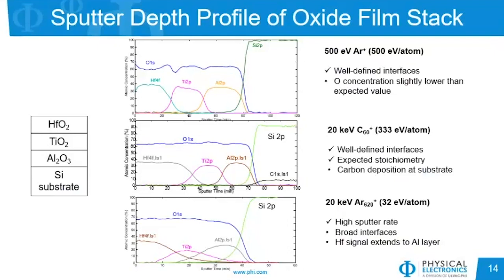So I'll point out that the stoichiometry for both the C60 and the monoatomic argon tend to be closest to the actual values. In the argon gas cluster at the bottom, we do see, for example, the titanium concentration is closer to 20%, where it should be more like 33%. We also notice that in the argon gas cluster, the interfaces are quite broad. And we even see hafnium that is being detected all the way down at the aluminum layer. Whereas for the monoatomic argon and the C60, we do see sharper interfaces for each of those. One thing to also note for the C60, there is some carbon that is deposited in the silicon substrate layer, which you do not see with the other two conditions.